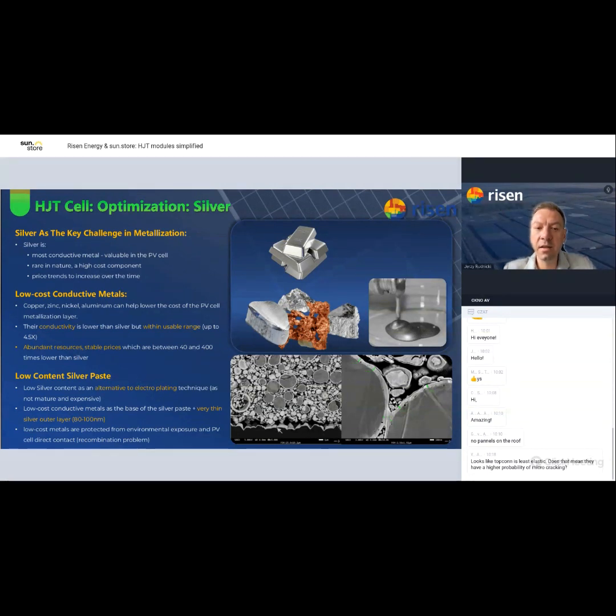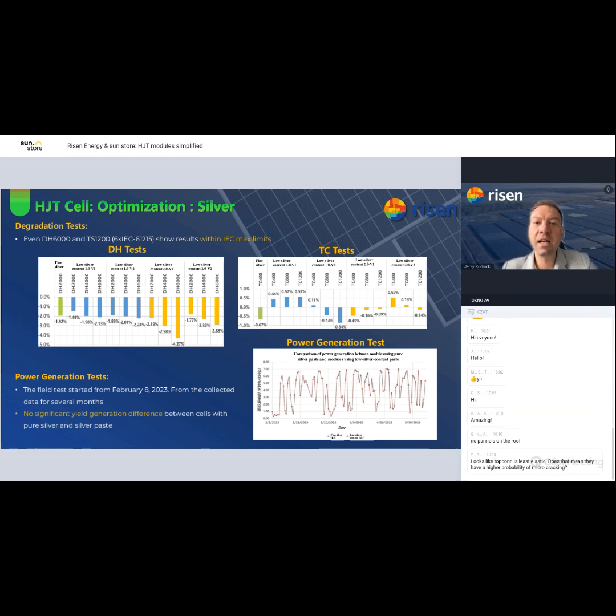So therefore, we are protecting the outer layer of the cell, which is being seen here as this dark bar at the bottom, from interacting with these low-cost conductive metals. So therefore, we are not contaminating the cell with those metals, which would basically decrease the reliability of our cell. And this low content silver paste is now being used by us with our HJT cells, and we have been testing these cells with different variants of this low silver content paste. And we are comparing these tests with the cells where we use pure silver as conducting material for the fingers. And we have achieved very good results, not lower than even pure silver, clearly within the IEC standards.